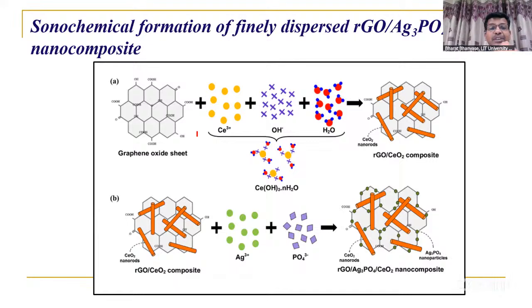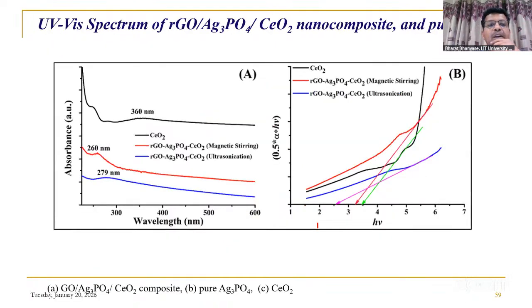So this is the mechanism. This is the graphene sheet here, on which cerium hydroxide forms, leading to the formation of RgO-CeO2 composite, in rod form. In the second case, AgNO3 and Na2HPO4 are added to this RgO-CeO2 nanocomposite, forming Ag3PO4 which is deposited on it. This is well validated by UV-Vis analysis.